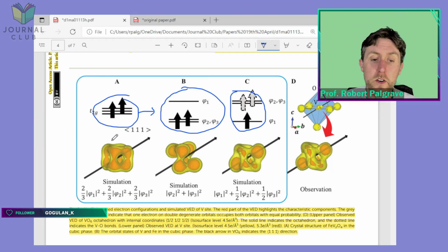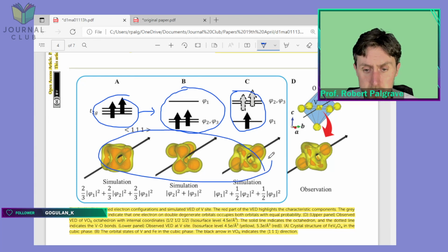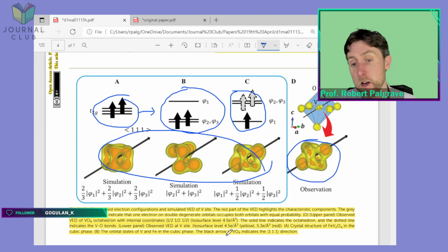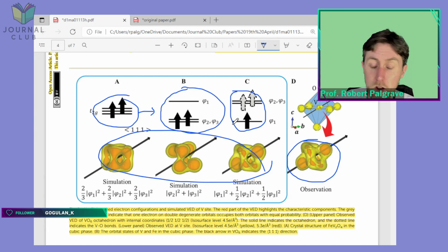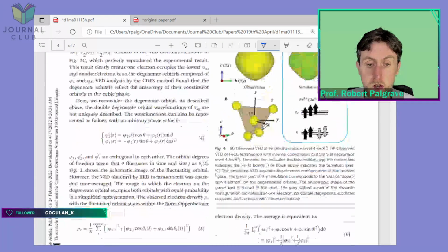But anyway. So all the ones here are simulated, but what they show here is the observed or measured result using their X-ray diffraction technique, and you can see it matches up pretty well with simulation C. So this strongly suggests, I would say, that the splitting of the orbitals is as depicted in C, with one orbital becoming more stabilized with one electron in it, and then the other electron is in either of those other two orbitals up here. Yeah, so in either of these other orbitals.